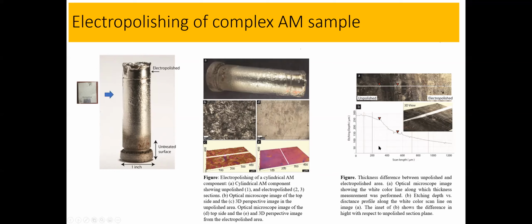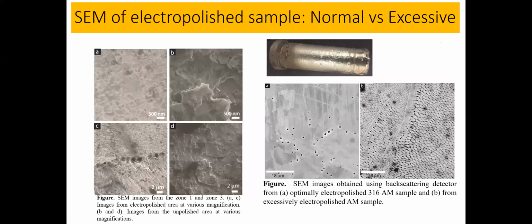One of the major contributions from our group is that we also figured out how much material one should remove in order to get a very smooth surface. This optical profilometry is done starting from point 1 to 3. I'm now on the rightmost figure, panels A and B. Panel B shows etching depth versus the scan length graph. When you remove almost 200 micron, your roughness reduces from a very high value to sub-micron scale roughness.